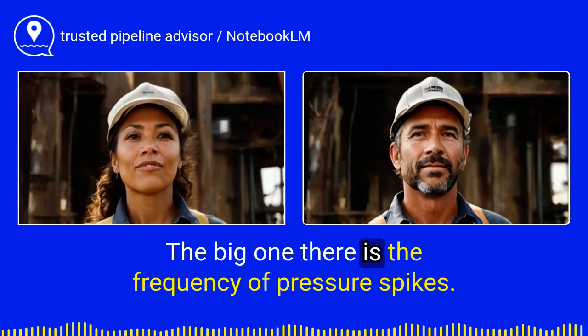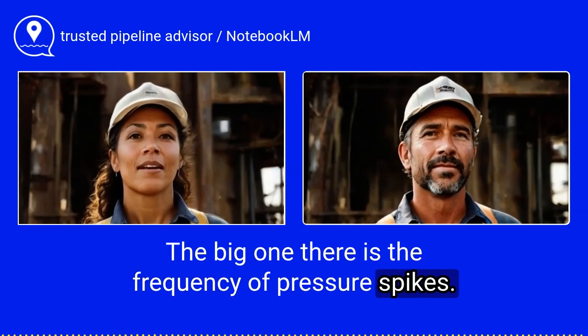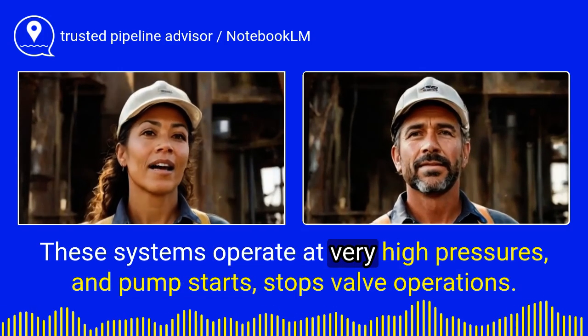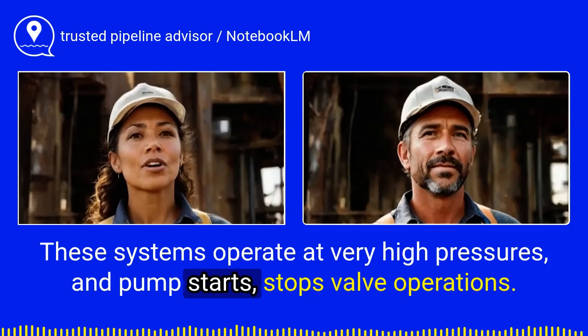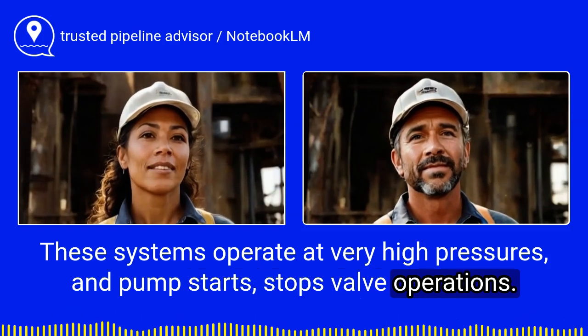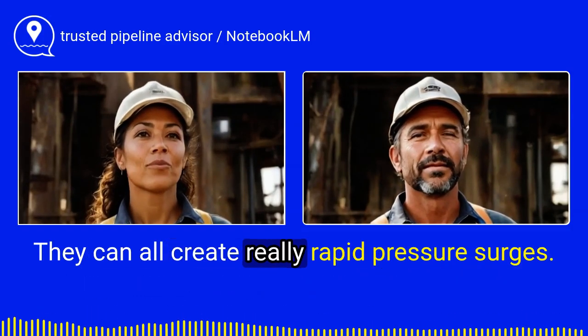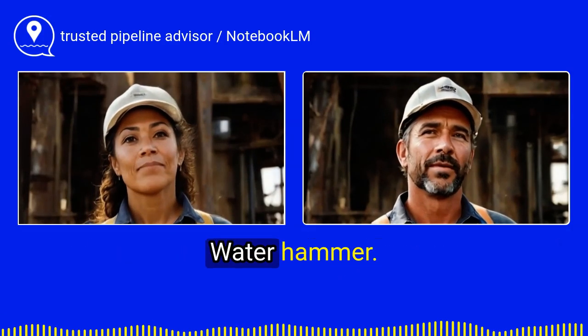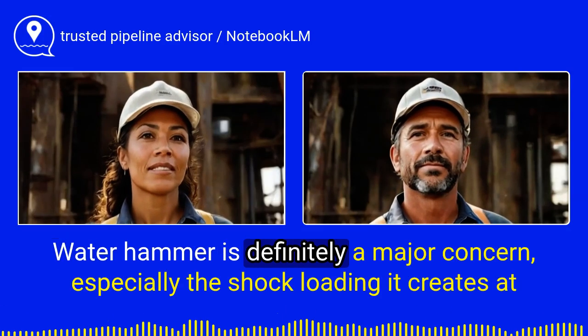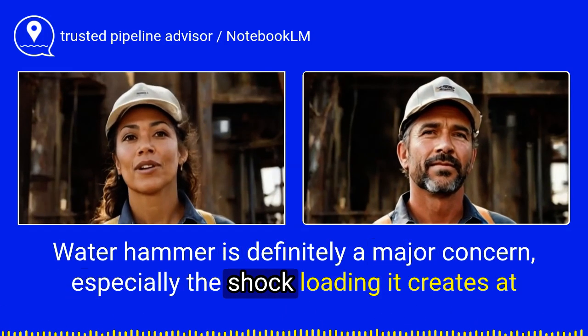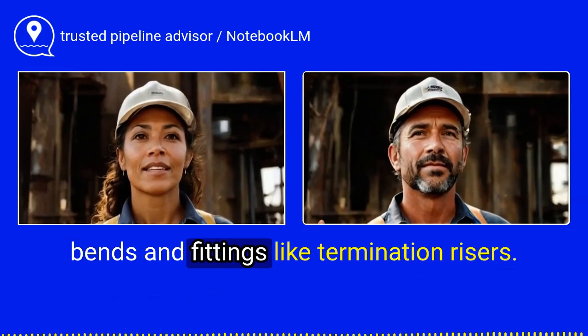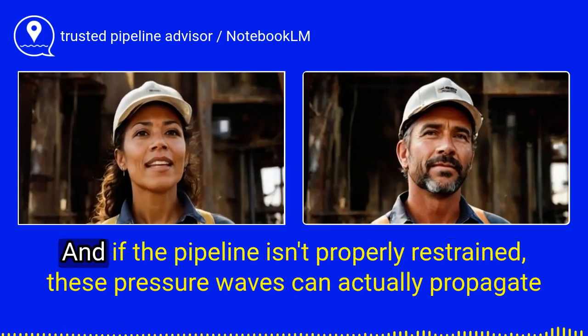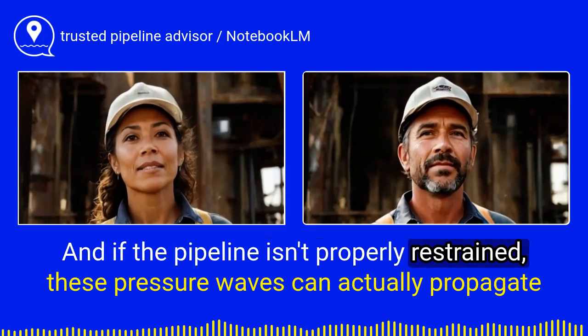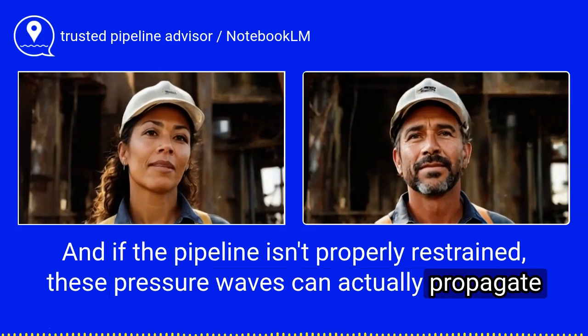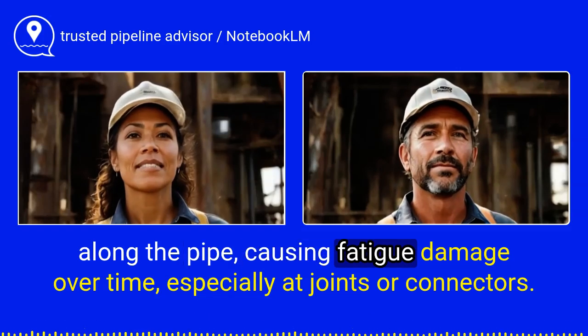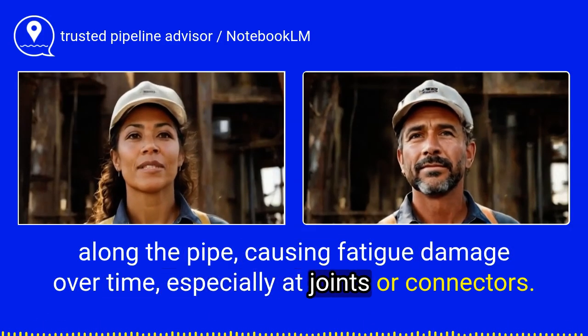The big one there is the frequency of pressure spikes. These systems operate at very high pressures. Yeah. And pump starts, stops, valve operations, they can all create really rapid pressure surges. Water hammer. That's it. Water hammer is definitely a major concern, especially the shock loading it creates at bends and fittings like termination risers. And if the pipeline isn't properly restrained, these pressure waves can actually propagate along the pipe, causing fatigue damage over time, especially at joints or connectors.